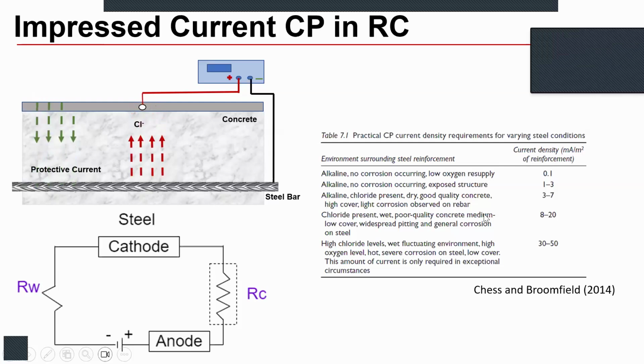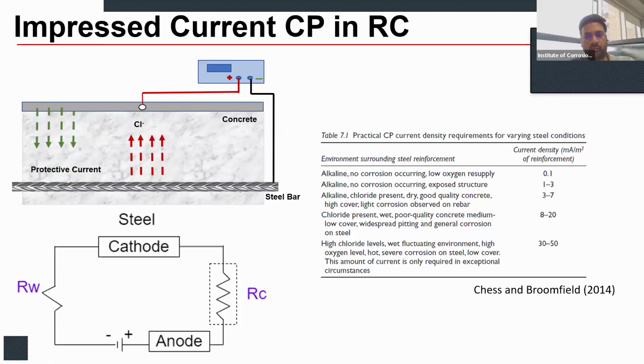This table gives us practical CP current density requirements for various steel conditions. When there is no corrosion happening, steel in concrete is still alkaline in nature, there's low oxygen resupply, so that means cathodic prevention conditions are there. The current density required is about 1 to 2 milliampere per meter square of reinforcement.